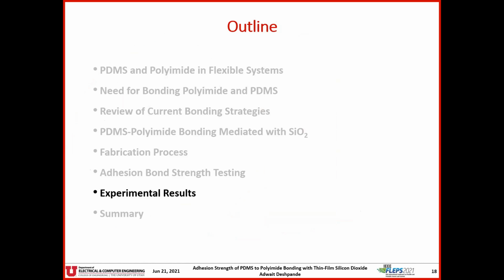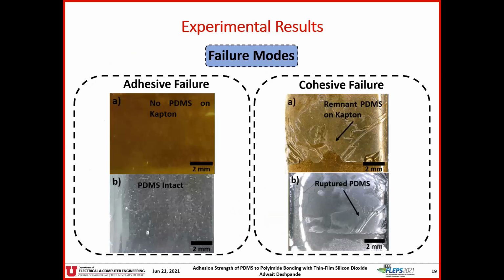Moving on to the results. Two different failure modes were observed: adhesive failure and cohesive failure. In cohesive failure, the PDMS ruptured before the polyimide PDMS interface, indicating that a strong bond was formed. In adhesive failure, the PDMS did not rupture and hence the bond was considered weak.